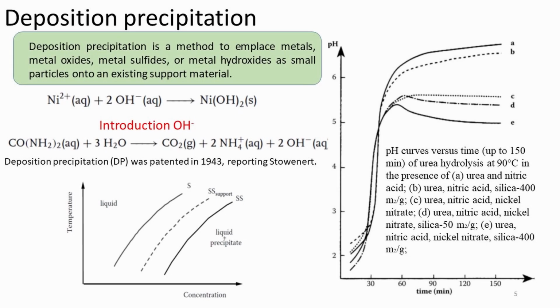The key point for successful deposition precipitation is the gradual addition of the precipitating agent to avoid a local rise of concentration above the supersaturation curve, which would cause rapid nucleation of the precipitate in solution. The interaction with the support decreases the nucleation barrier, so at concentrations between those of the supersaturation curve SS support and SS, the compound exclusively precipitates onto the support surface.